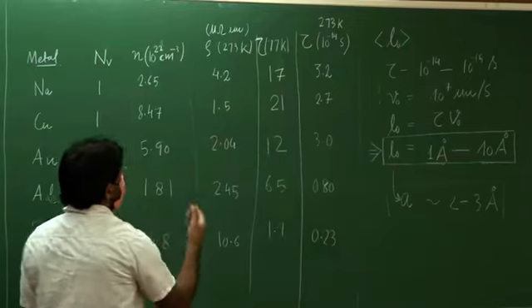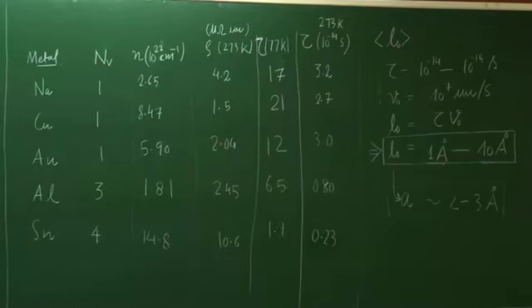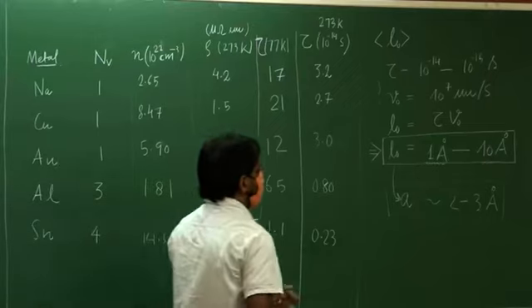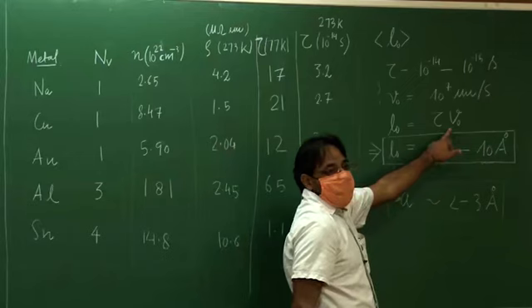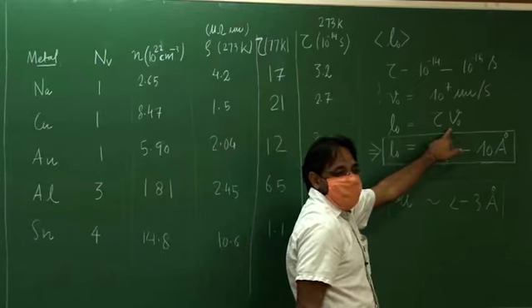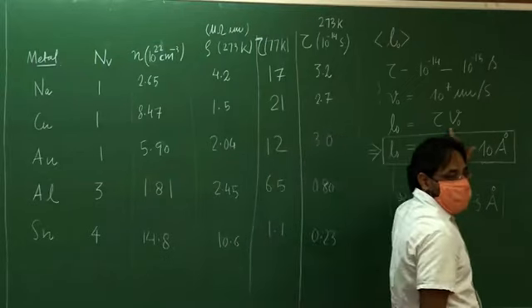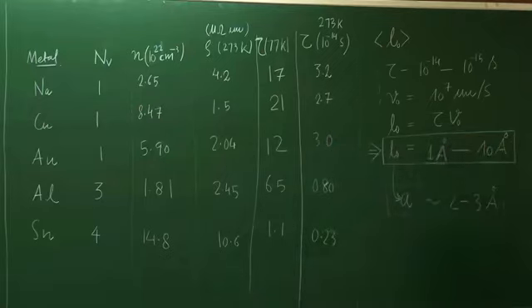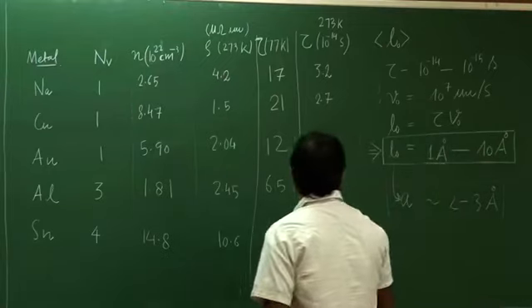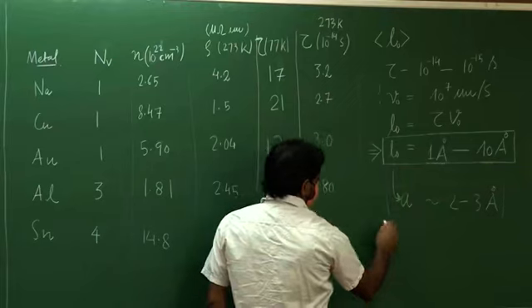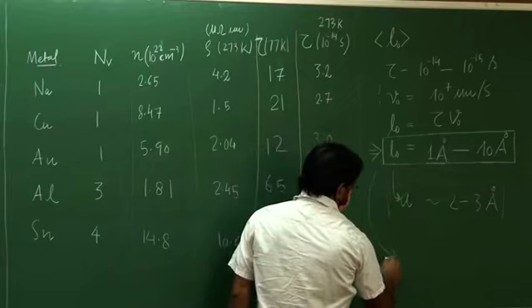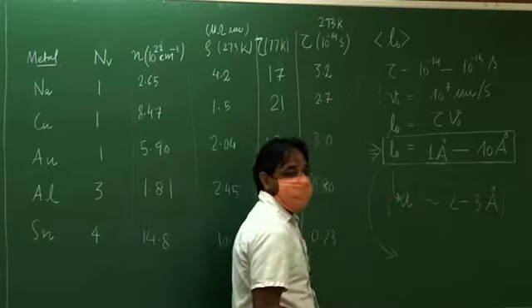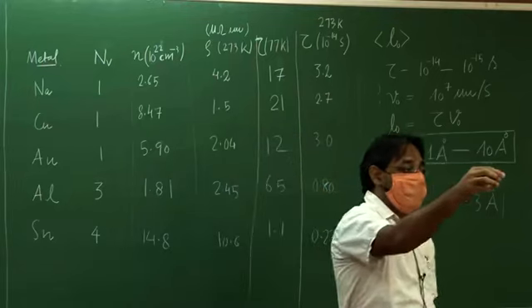So what do you see? You see an order of magnitude increase in tau naught. If tau naught increases, v naught will not change much, because you haven't changed temperature much in going from 273 to 77. If you again use half mv squared equal to 3/2 kT, you will get the same order of magnitude for v naught. It's not that it will change by an order of magnitude, right? So you will get l naughts, mean free paths, that are of the order of 1000 angstroms. That means an electron is not colliding until it travels